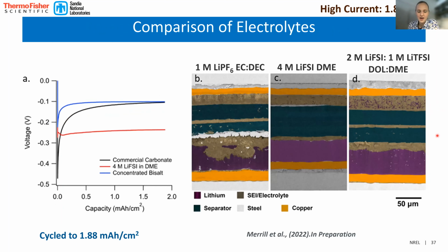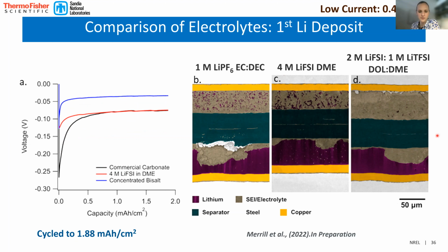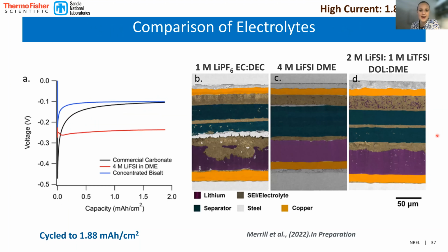Okay, if we go to high rate, so that was done at the low rate of 0.47 milliamps per centimeter squared, at a high rate of 1.88 milliamps per centimeter squared. What you can see now is a lot of similar characteristics. We're seeing, again, there is some gas that had formed in the EC-DEC case, and there's some reaction with the separator in a form of a layer in between the separator layers.